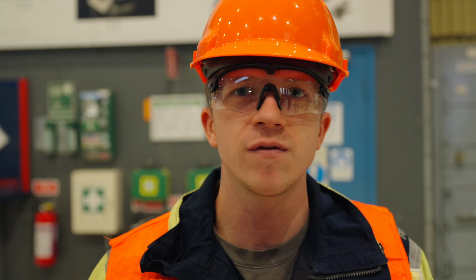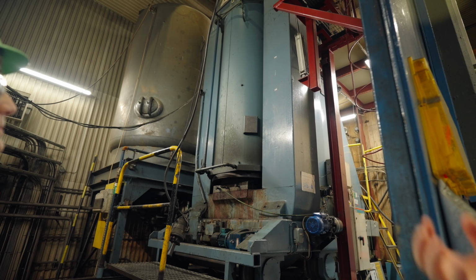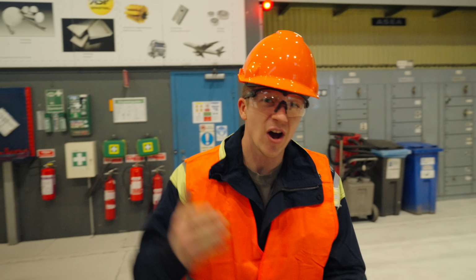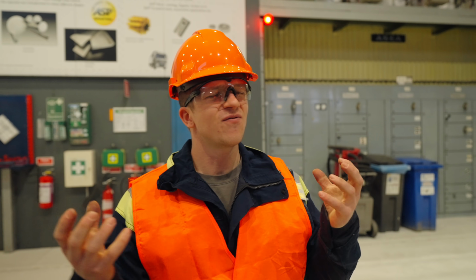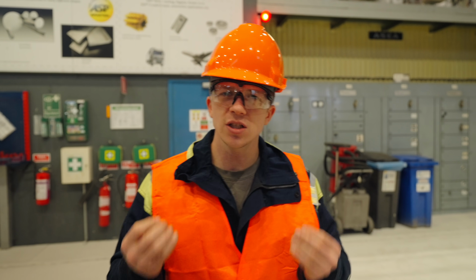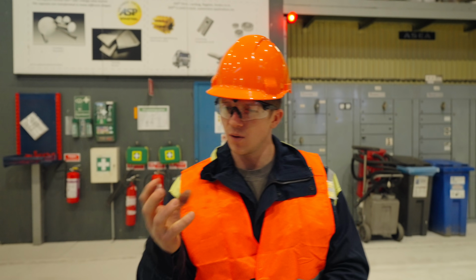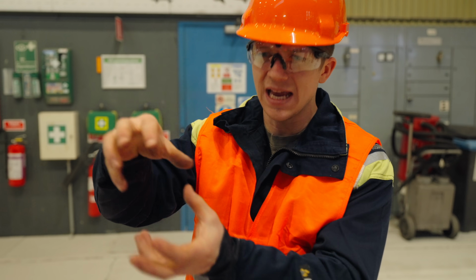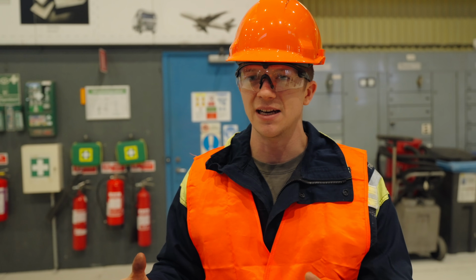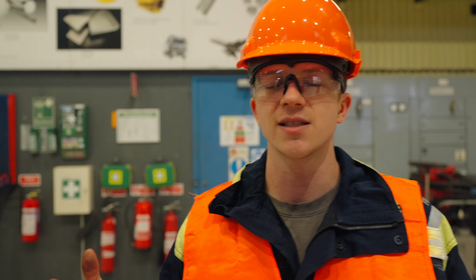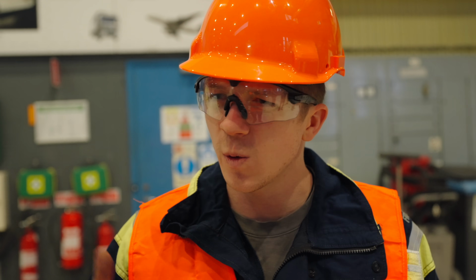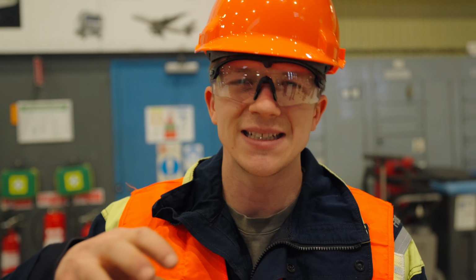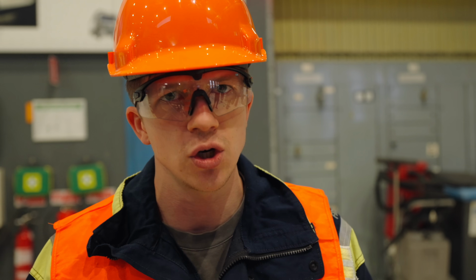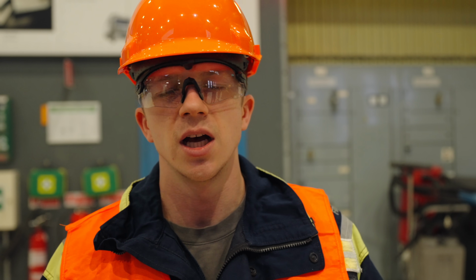There's thousands of bars of argon pumped into a chamber where, with the hot argon and with temperature heating it, it forms into a solid. And it doesn't quite make sense to me. But when you put that capsule in and you pressurize the outside to those thousands of bars, without a hammer or an anvil, without a power hammer, without a press, it will compact it and effectively create a diffusion bond of the powder and turn it into a solid.